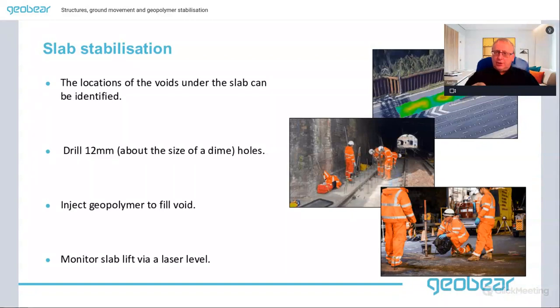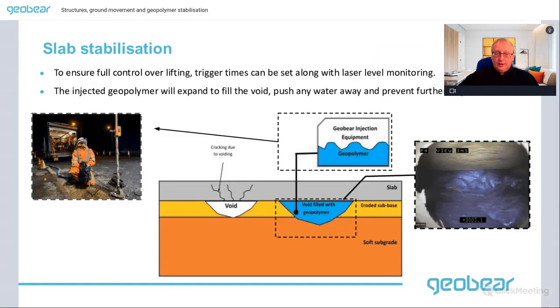But you can see that the injection is done using very lightweight equipment and with minimal disruption. And so we can do the work very quickly, get in and get out without the need for long possessions or road closures, and improve the conditions underneath the pavement, underneath the slab, and thereby extend its life. This shows you a little cartoon drawing of a void under a slab, and we just drill a hole, put the polymer into that void, and it sort of works. There's a picture there that shows we got a camera inside underneath the concrete slab. You can see the polymer expanding as it migrates through that void.